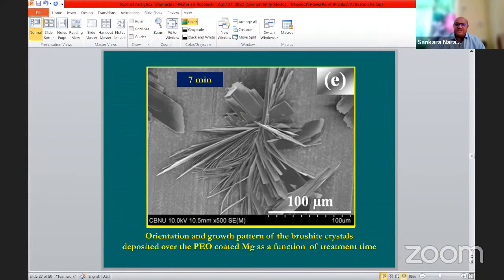After 7 minutes, you can see it is attached and then it is growing like this. So you can see the evolution of the growth pattern of the crystals very well by monitoring with scanning electron microscopy as a function of treatment time. Take the samples at different time intervals and take scanning electron microscopy pictures to understand the mechanism of how the crystals are developing over the material.